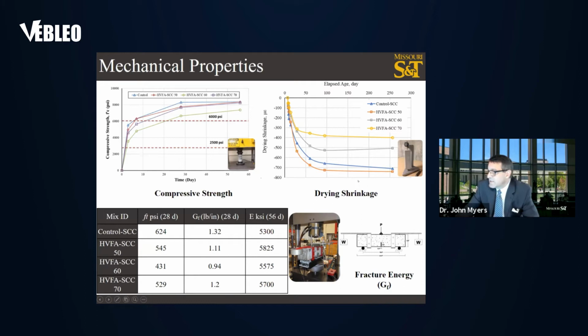In addition, you can see the drying shrinkage behavior. Worthy of note is that the high volume fly ash SCC had the least amount of shrinkage, which is a good thing. And then you can see the results in terms of the tensile properties as well as the fracture energy. And you can see the test for the fracture energy shown in the bottom right, as well as the modulus of elasticity or stiffness of the concretes for these various mix designs.